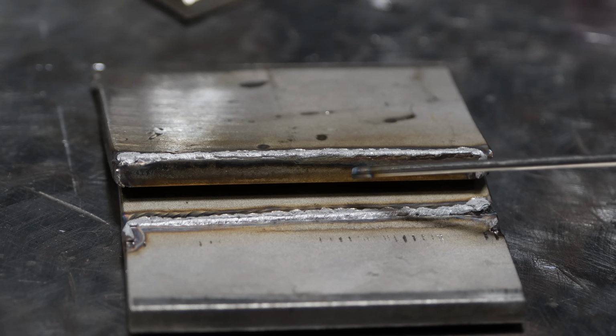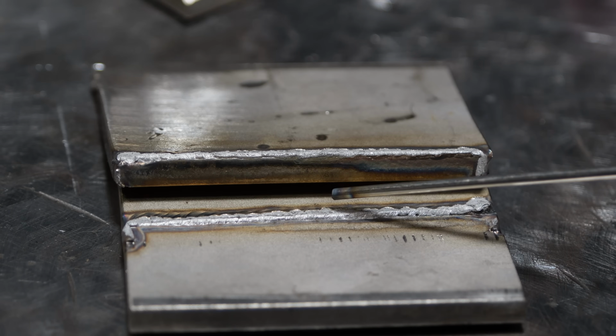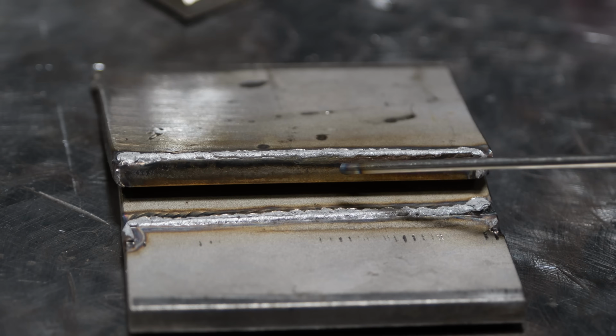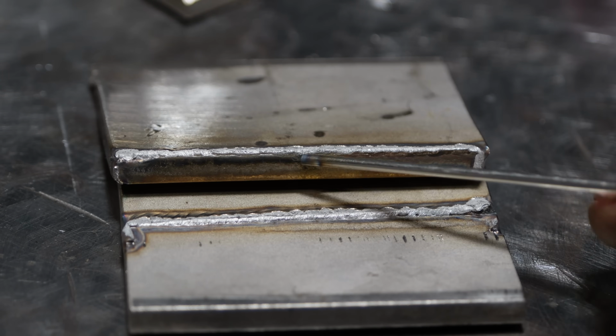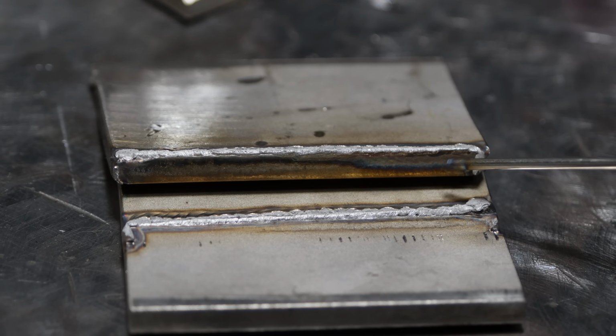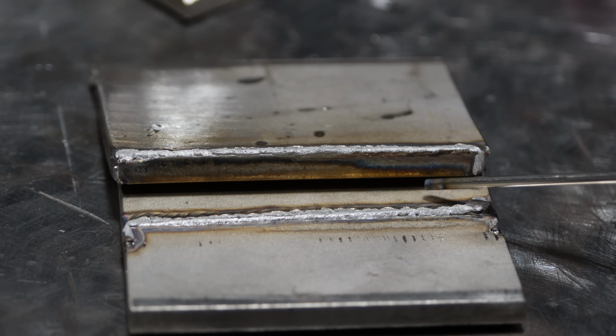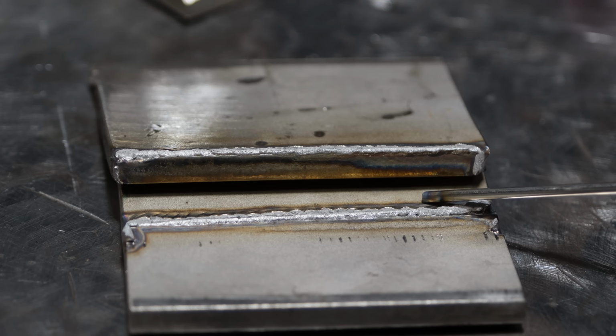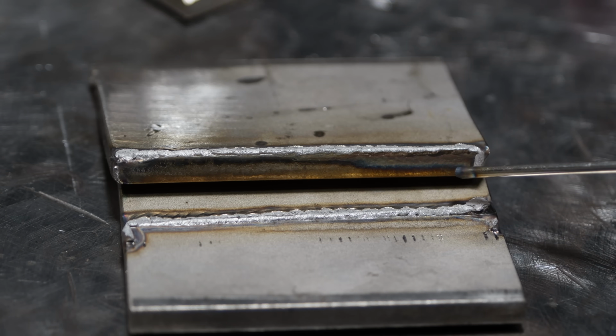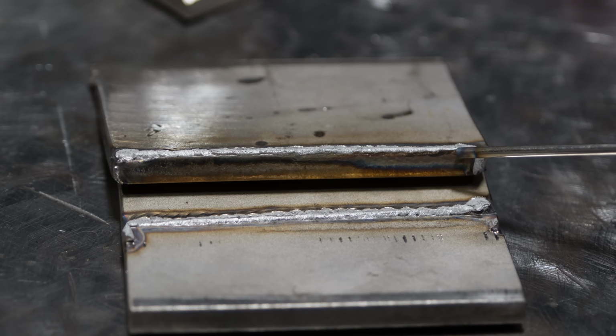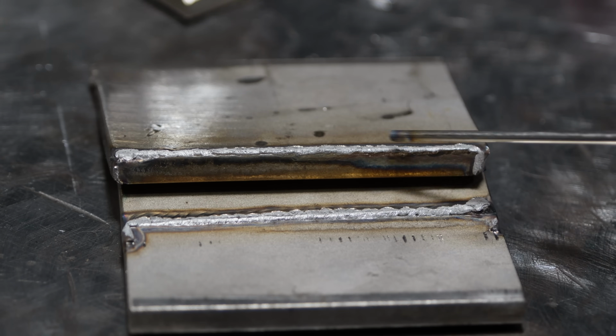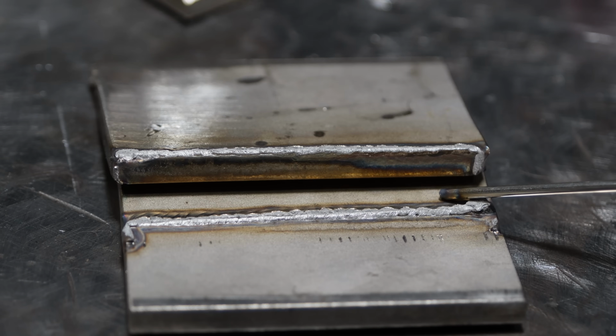You don't want to go so fast that nothing fuses and just say lay wire and just go super fast. So it pays to do a break test like this just to see where you're at. If you see that original edge of the plate completely unbroken down, that's probably a good sign you're not using enough heat or you're moving too fast. Based on what I see here, the weld is 100% clean. The original plate edge here was broken down. There's, again, not much penetration, but everything looks good start to finish. This would be an ideal result.